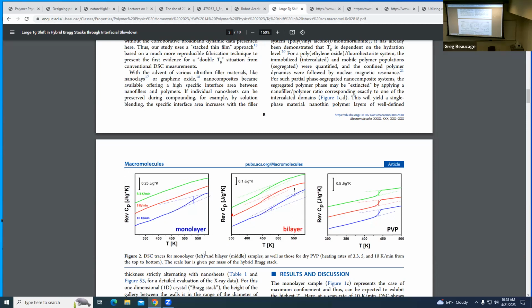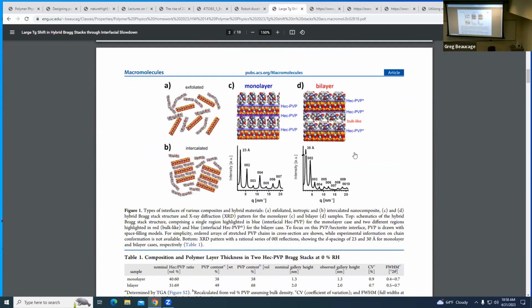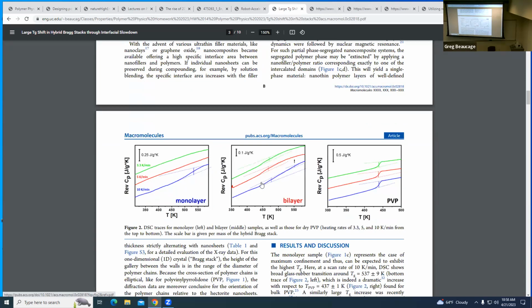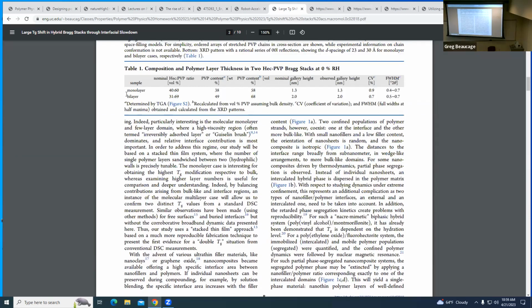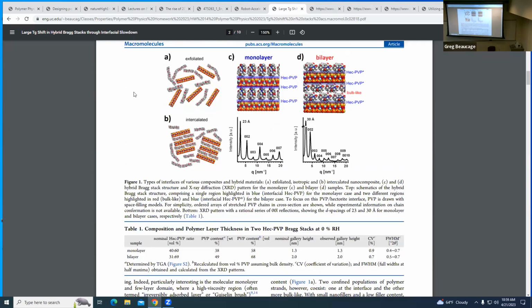And also when he has a bilayer, and he has this bilayer structure, he's got two polymers within it. Then he gets two Tgs, and he says one of them is a bulk Tg and one's the other one. So he's saying there's a Tg here, and there's a Tg there, so it's two Tgs. So this Tg's at 445. So these Tgs are all at higher temperature. That means that they're stiffer. So it kind of makes sense that it would be at a higher temperature because it would be stiffer because it's confined. So when the polymer is stuck in there, it's not as easy for it to wiggle. The Tg is kind of where it starts wiggling.